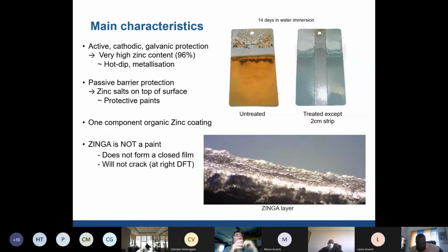So the passive barrier protection is very important. And the nice thing is it's automatic. You don't have to do anything. You just leave the zinc outside in the weather, and it forms the barrier coating. And apart from the toughness of the coating, the formation of carbonates on and inside the zinc film increases your adhesion. Normally after 7 days of outside weathering, in the rain and the wind, if you do a pull-off test with a hydraulic puller, you're getting about 6.3 megapascal. But after 3-4 months, it goes up to 9 megapascal, and after 12 months, it goes up to about 11.2 megapascal. That's extremely high, because thermal zinc is only 5 or 6, and Zinga is sitting at 11. So the adhesion strengths are phenomenal.